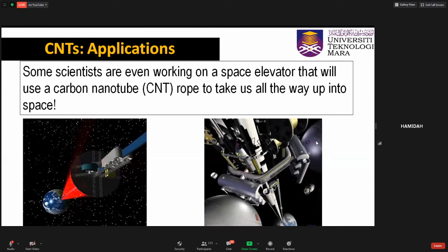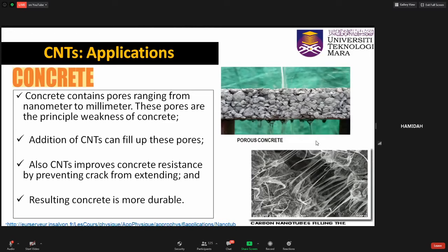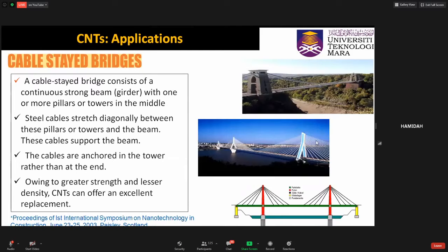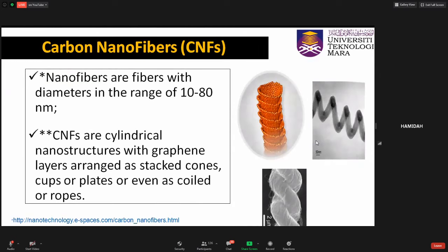CNTs have been used to fill up pores in concrete that range from nanometer to millimeter size, resulting in more durable concrete. Owing to greater strength and lesser density of CNTs, they can offer an excellent replacement to conventional steel as cables in cable-stayed bridges. Carbon nanofibers, or CNFs, are fibers with diameter in the range of 10 to 80 nanometers. CNFs are cylindrical nanostructures with graphene layers arranged as stacked cones, cups, or plates, or even as coils or ropes.